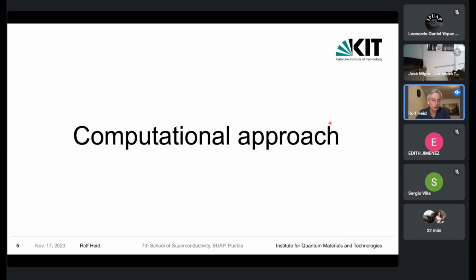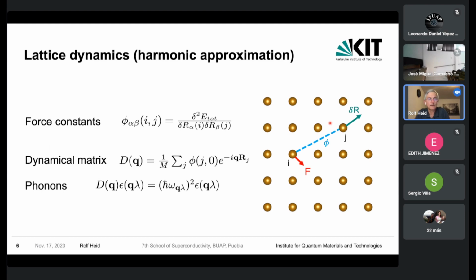Let me start with the computational approach. As you may all know, the basic ingredient one needs to understand vibrational properties in solids is the so-called lattice dynamics in harmonic approximation. And the basic quantity needed here are the so-called force constants, which are the generalized spring constants in such a crystal. In practice, they can be obtained by the second derivative of the total energy of a system with respect to atomic displacements, which provide the perturbation of the otherwise idealized crystal. Now, the Fourier transform of the force constants is the dynamical matrix, which by diagonalization provides the basic quantities of the quanta of vibration, namely the phonons. The eigenvectors are the displacement patterns of the phonons, and the eigenvalues provide the frequencies of the phonons.